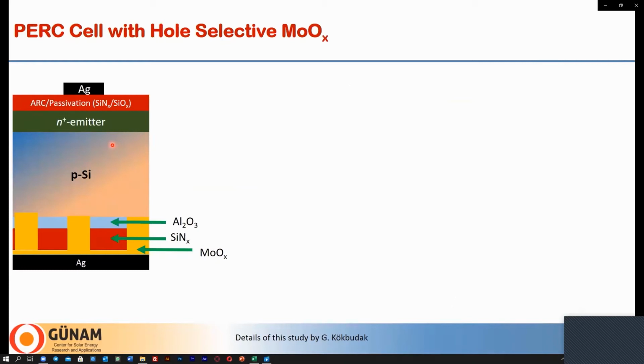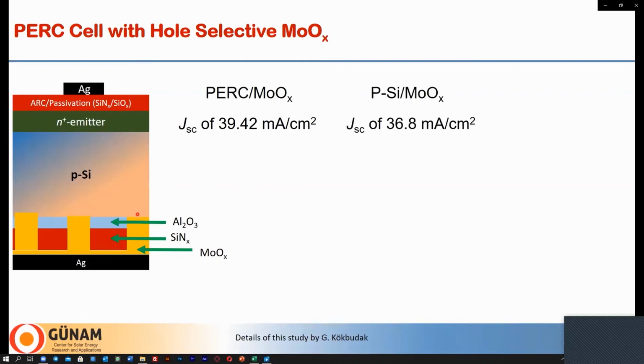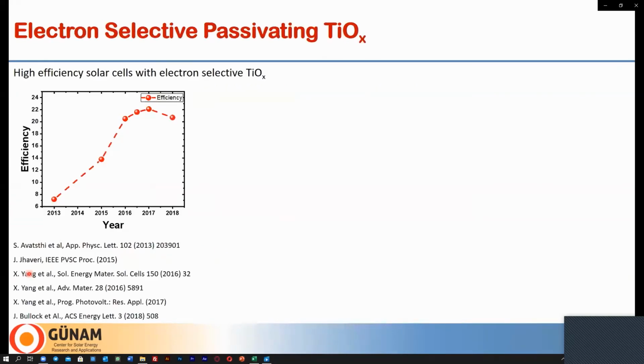And we did this experimentally. And you see here that molybdenum oxide now replaces the local aluminum back surface field in the standard PERC structure. And we obtained experimentally a short circuit current density of more than 39.4 milliamps per centimeter square, which is higher than what we get from a direct heterojunction between molybdenum oxide and silicon. And more details about this structure will be presented later today by Ms. Gamze Kokbudak. Now I would like to summarize our results on electron selective titanium dioxide that we prepared by ALD.